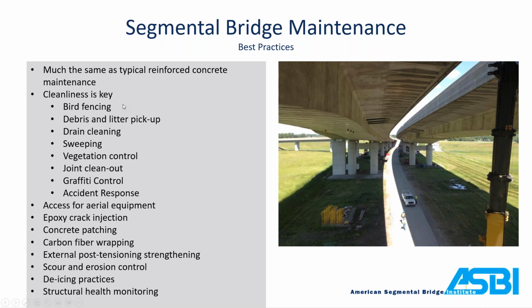Like I said, you got 12 inches of movement at these expansion joints. The maintenance guys on Zilwaukee had a system that the fencing, the bird fencing, we call it, actually slid, expanded and contracted with the bridge to keep those out, so it wasn't a constant maintenance headache. But if birds or other critters get in there, they can make a mess of it pretty quick. Bird droppings hold moisture, which is bad. It starts deteriorating your concrete, your steel.